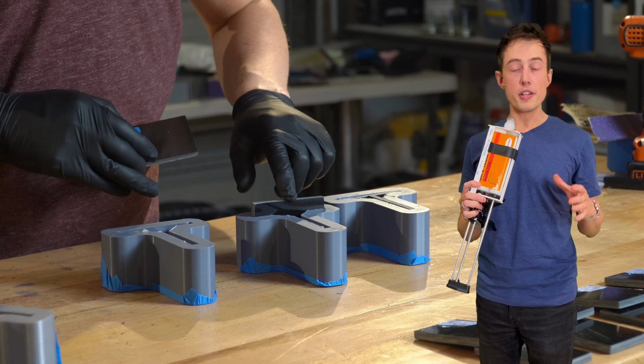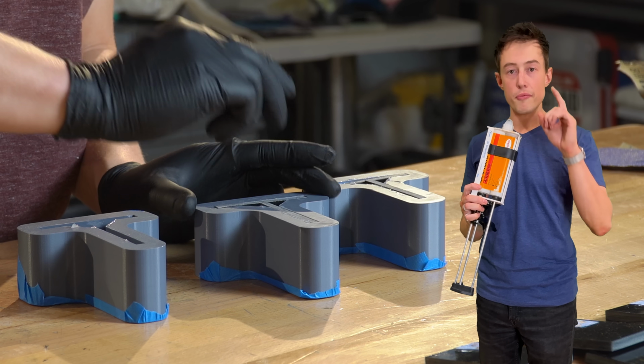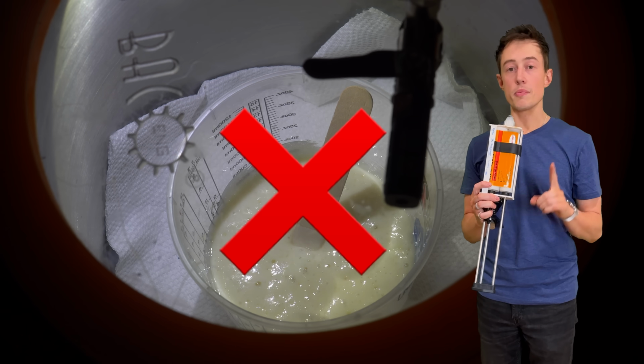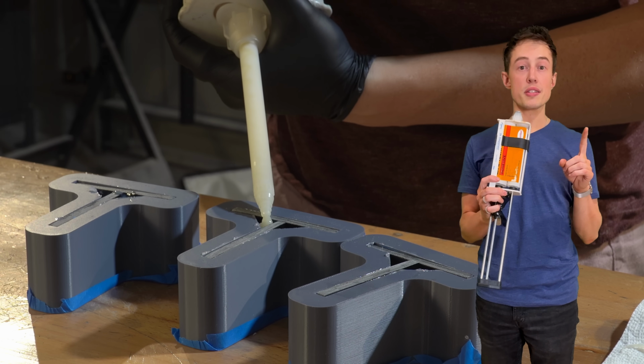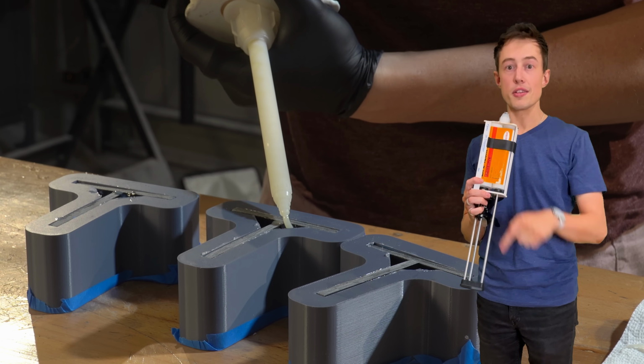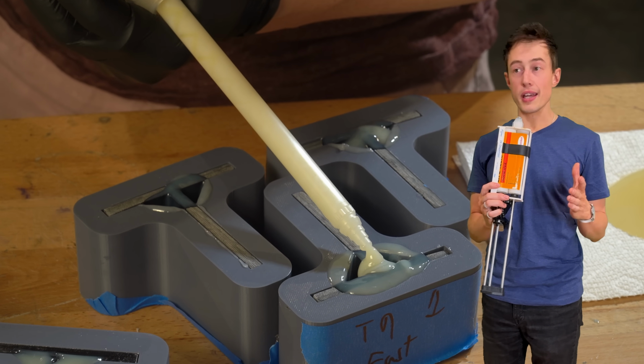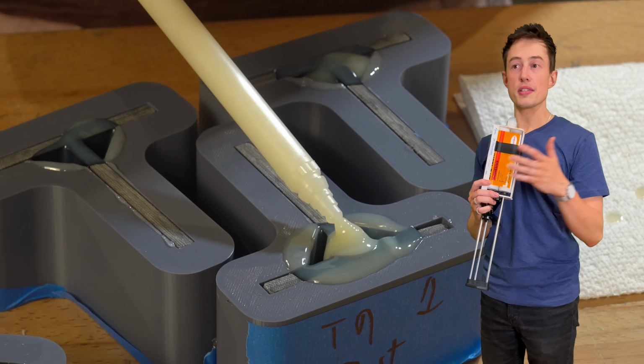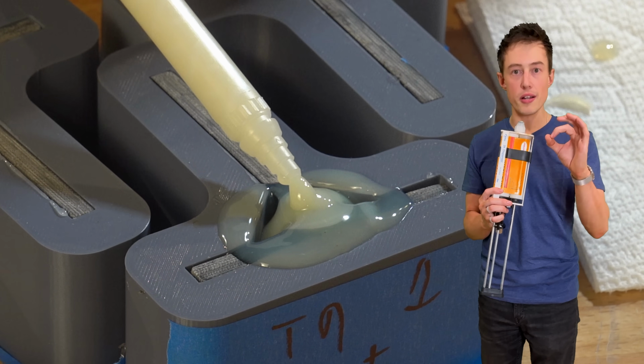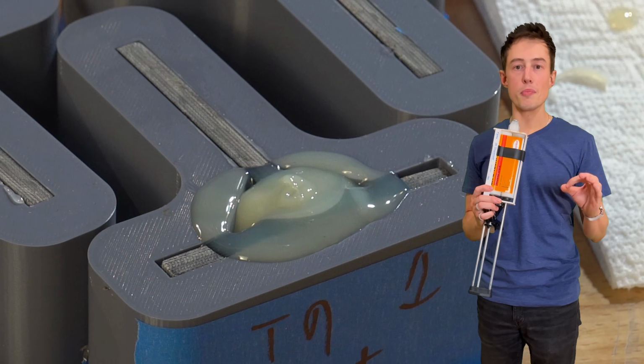For the next 3 coupons, I'm going to run everything the same except for one step. We're not going to vacuum degas in the cup, we're dispensing the epoxy through the mix nozzle directly into the mold. My hope here is that once again we'd find some extra strength by depositing the freshly mixed epoxy right onto the surface within a single-digit number of seconds.